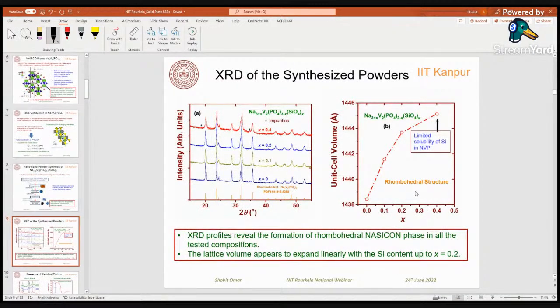So here are the XRD patterns of the synthesized powder. You can see that x equal to 0 is basically your NASICON structure, the rhombohedral NASICON structure, and when you add 0.1 and 0.2, there are no such impurities present in these compositions. But at x equal to 0.4, there are some impurity peaks present in this material. So one can see that there is some solubility limit of silicon inside this NVP, right? We have also calculated the unit cell volume, and we have seen a linear increase in the volume as we add silicon inside the material.